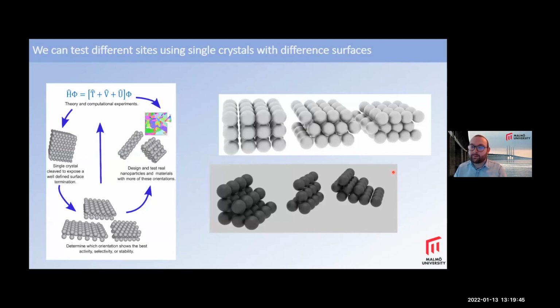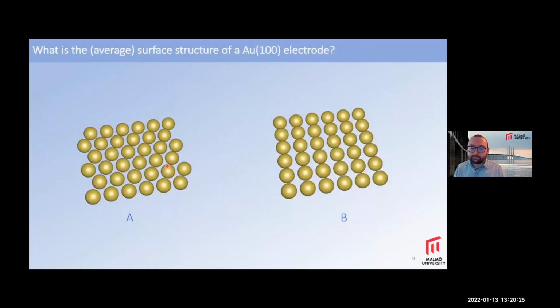We can test various different sites, and one strategy is to use different single crystal surfaces. You can imagine that you take a crystal and cut it in a certain direction, then test your chemical reaction on these surfaces and see what kind of reactivity or selectivity you get. Then you feed this knowledge back into theory, and you can use theory to maybe design real catalysts. Of course, this is a massive simplification of reality, but we have to choose some strategy, and this is perhaps one simple approach.